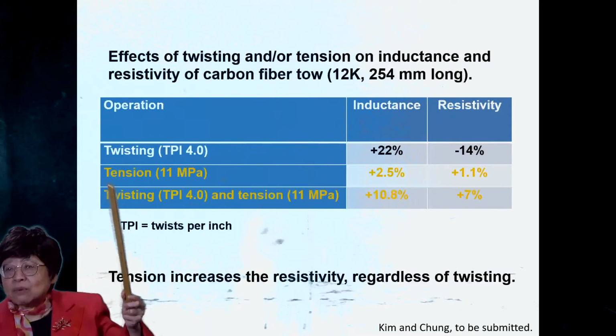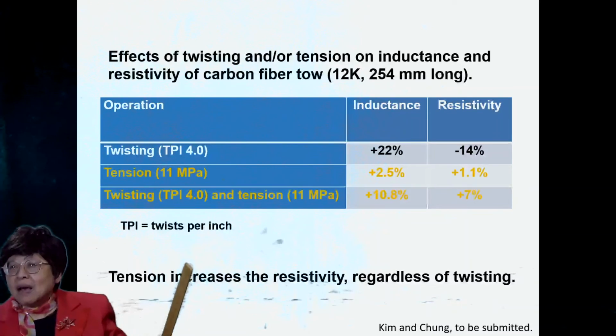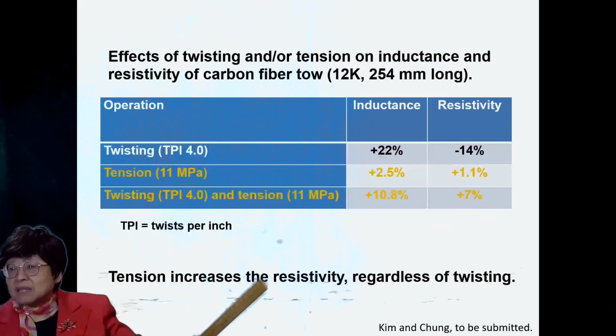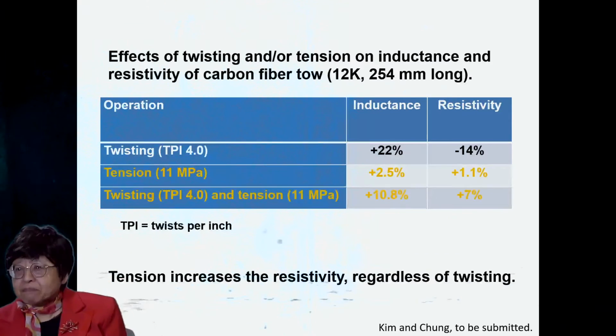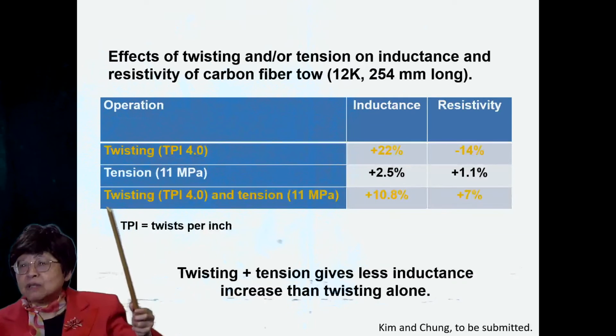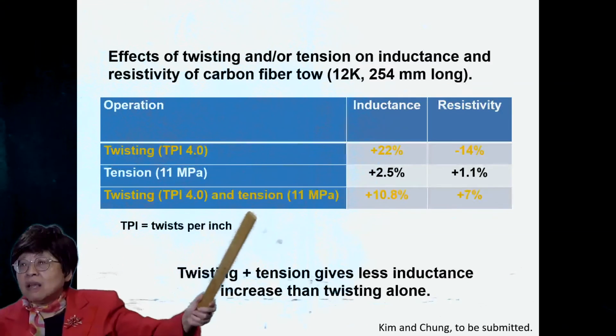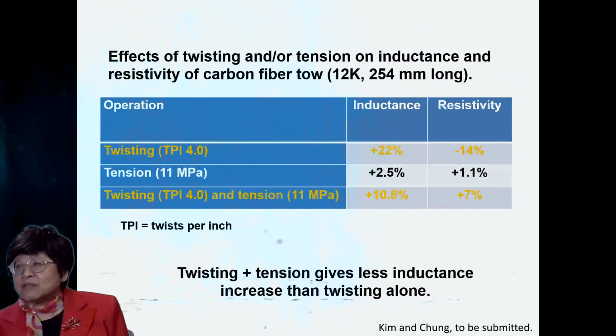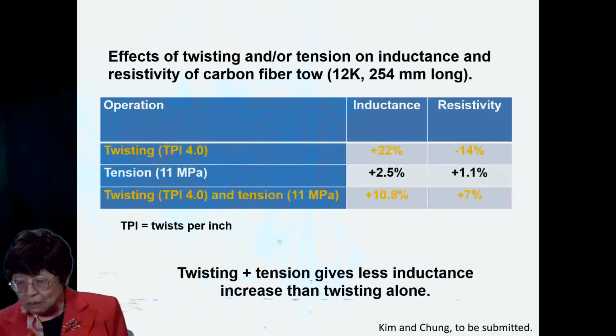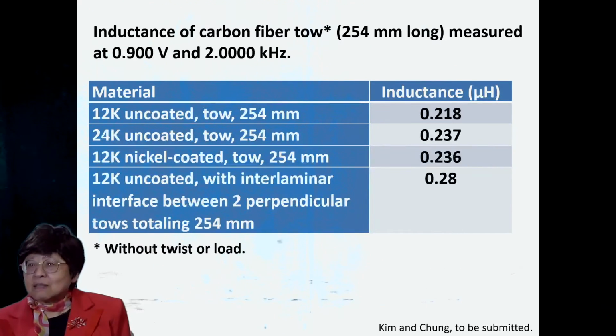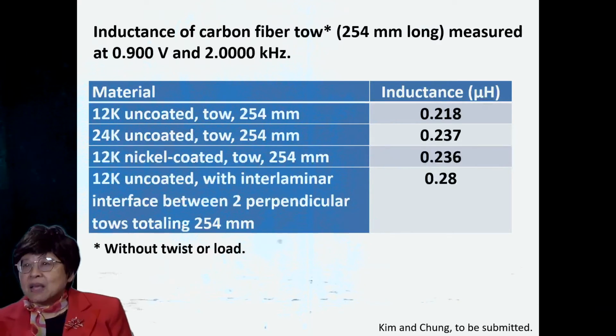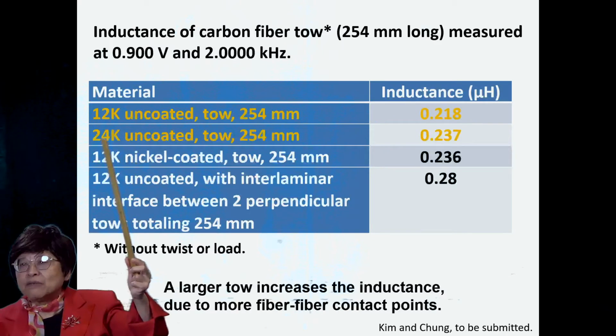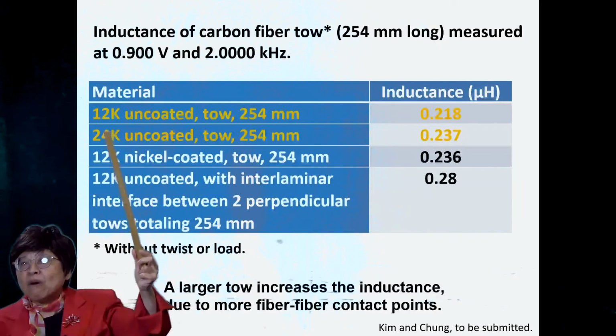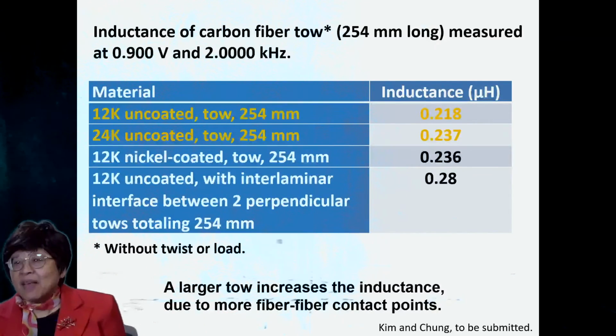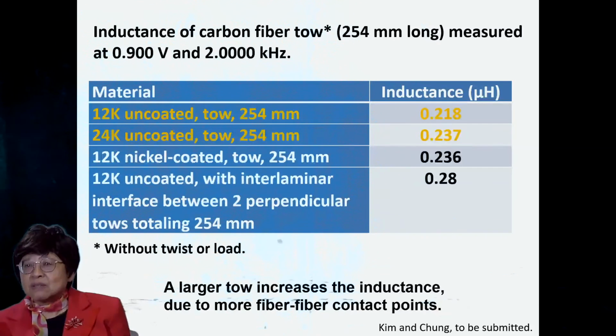Let's compare tension alone versus tension plus twisting. And the tension increases the resistivity regardless of the twisting. Comparing twisting versus twisting with tension, one sees that twisting plus tension gives less inductance increase than twisting alone. Let's look at the actual inductance values rather than just the fractional changes. Comparing the 12K and 24K fibers at the tows, having more fibers in the tow gives you more inductance. And that makes sense because a larger tow would increase the inductance due to more fiber-fiber contact points.